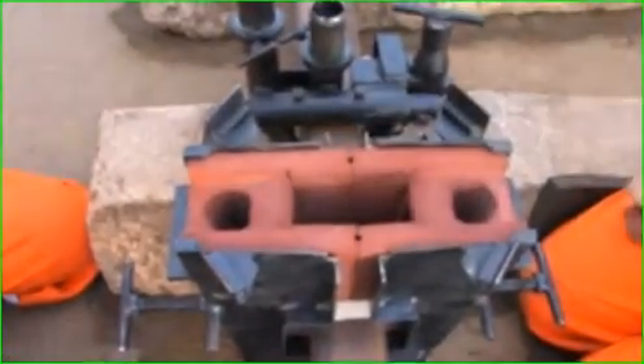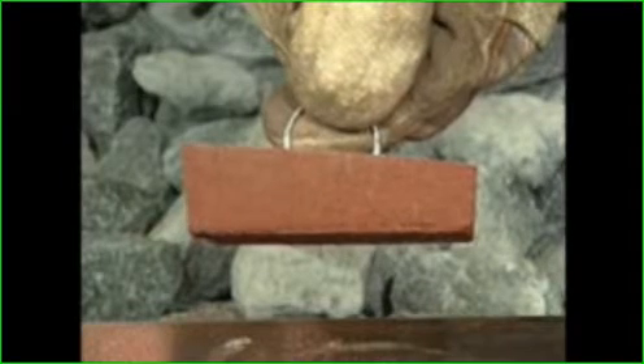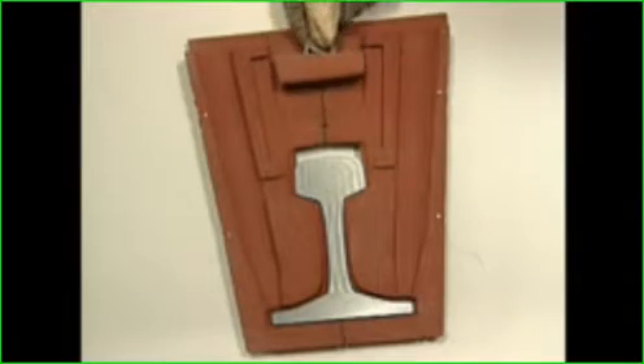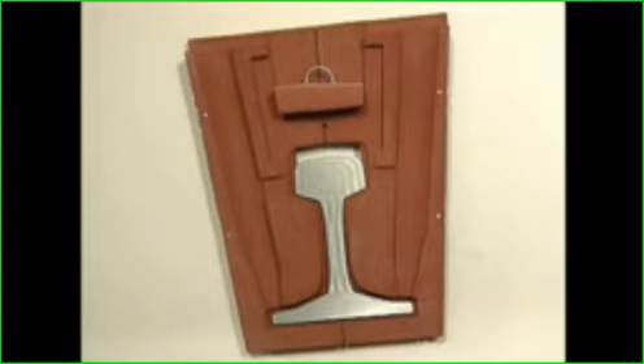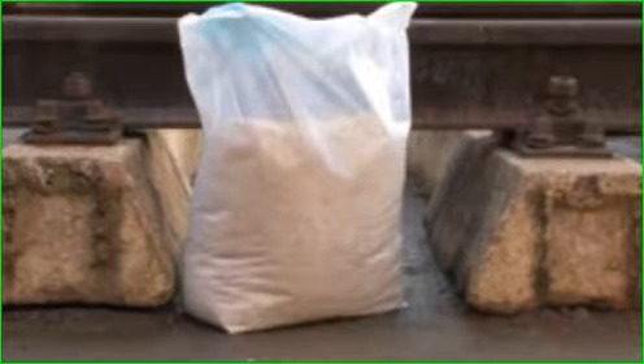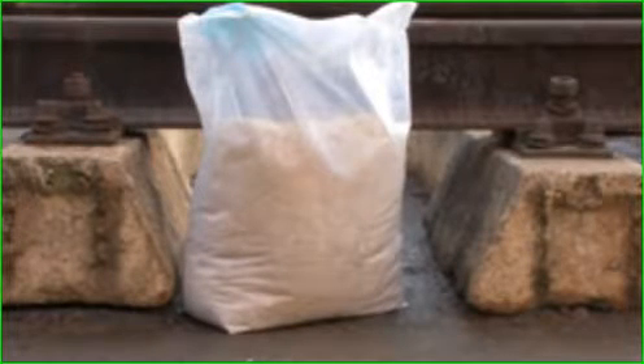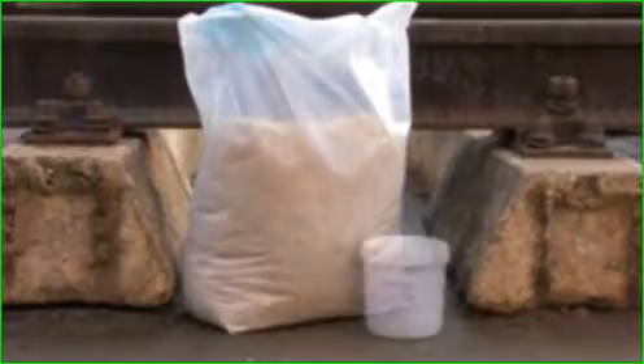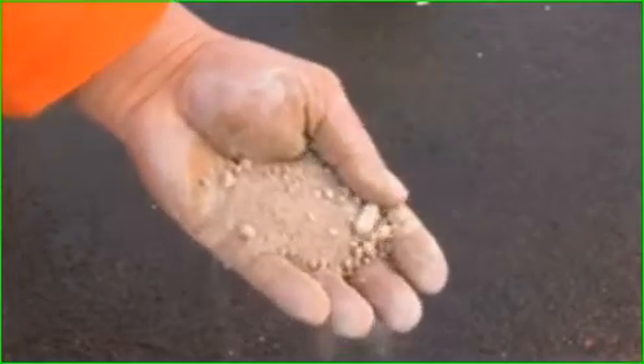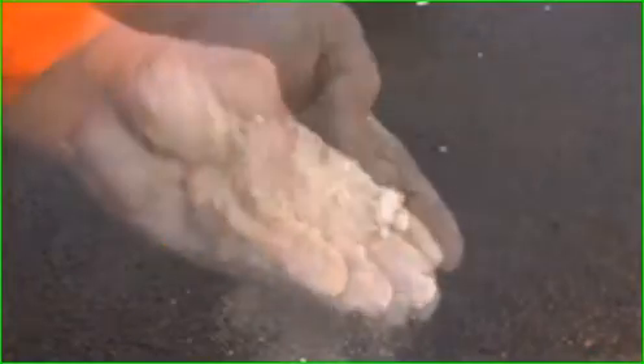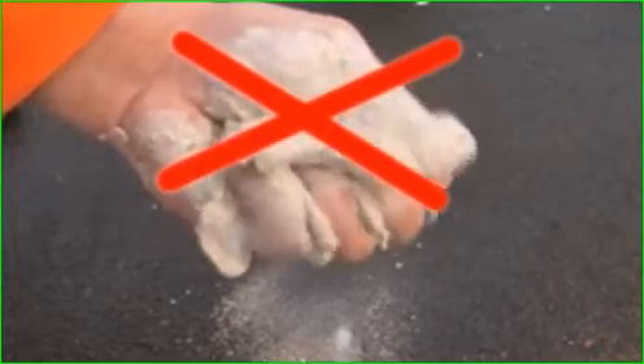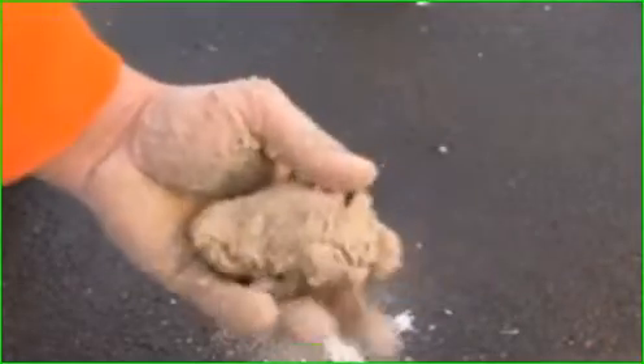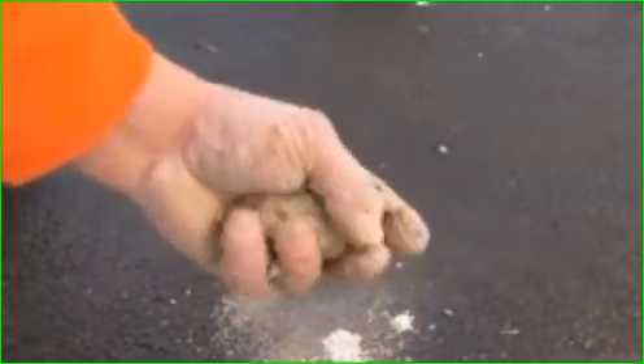When welded in curves, the rails are canted. The steel shall pour equably over both plug ends into the moulds. Thus the top surface of the mould plug must be filed to ensure that it is horizontal when fitted into the mould. For sealing the moulds, either luting sand or luting paste is optionally available. Luting sand shall not be too dry or too moist. It should be well kneadable.